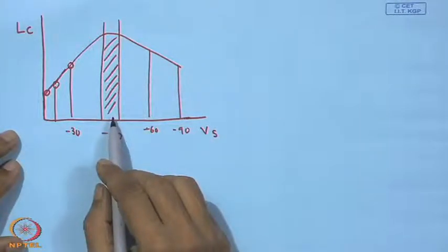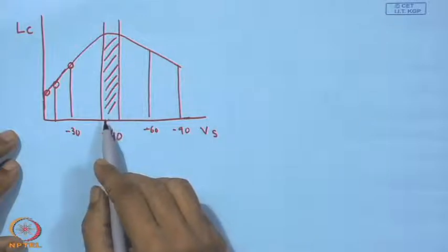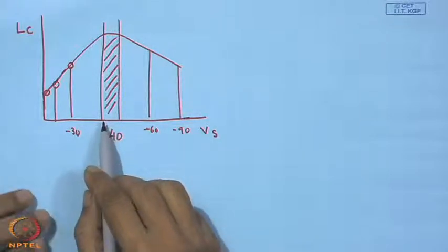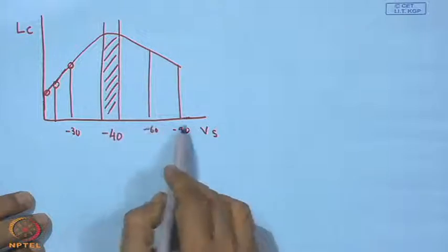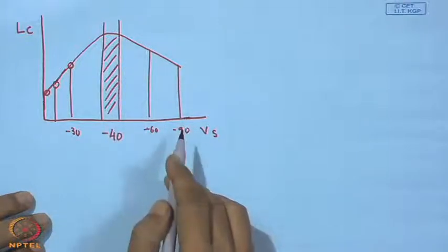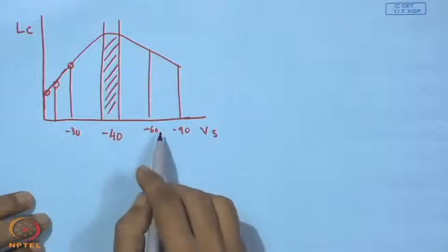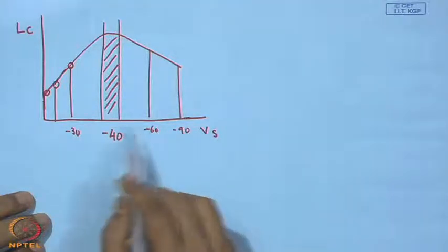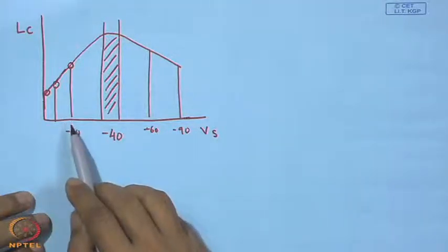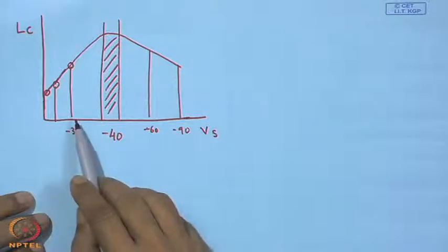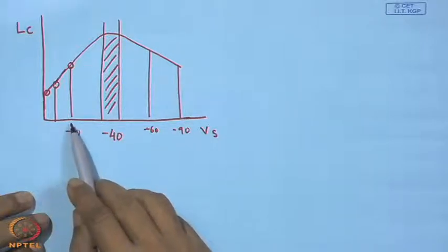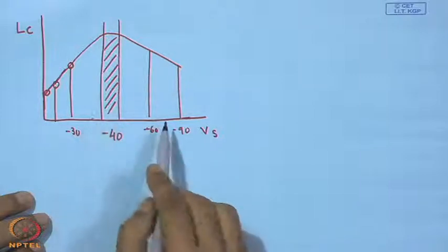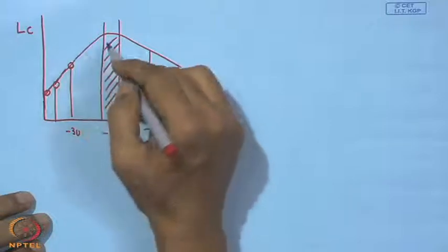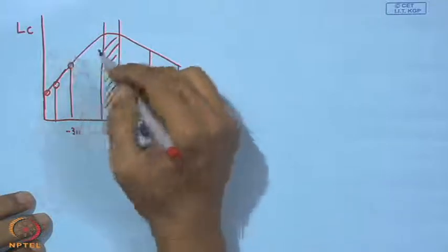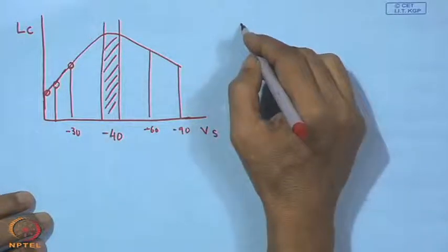Too much stressing at the interface, and also, because of very high energy availability, too much diffusion or a diffusion layer. And on this side there is no diffusion. So, no diffusion or too much diffusion, both are counterproductive. So, a value in between could give one of the very best results so far as adhesion is concerned.